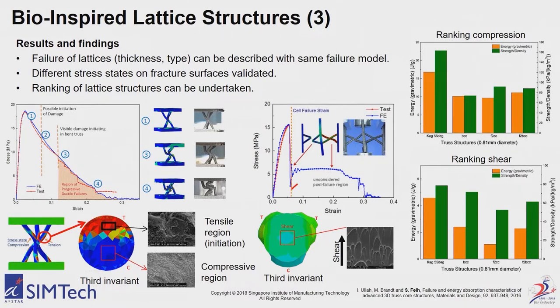And generally what we found was that the Kagome structures performed better than other types of lattice structures. So that was giving us a nice indication. From this work, we actually validated what good lattice structures look like, and we also proved that the ductile failure models for bulk material apply for very thin diameters as well. And that was something quite novel because nobody had actually done that at this point. But of course, we can go further.